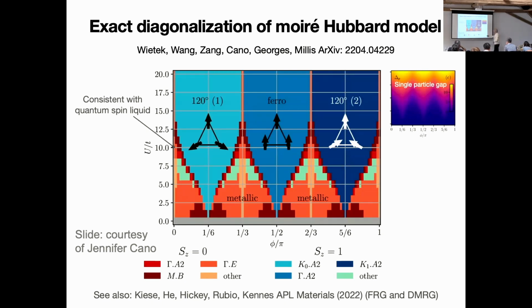Happily, the overall structure of the magnetic phases is in pretty good agreement with what I showed you before. This is, of course, finite size, so it's a little bit hard to extrapolate to what happens in the thermodynamic limit. But just from the level crossings that occur in the ground state, there is some indication here, at the boundary between the ordered phase and the 120-degree order, that perhaps there should be some sort of different state at the boundary. That state seems to be particularly strong at small U, near these. A small phi, you mean? Yeah. Small U. Oh, near the Van Hove. Yes. This is a very interesting region. This is not fully explored yet. It's a very interesting region.